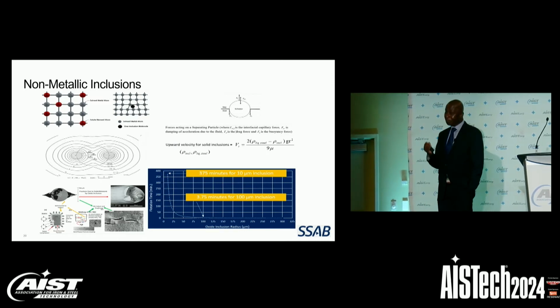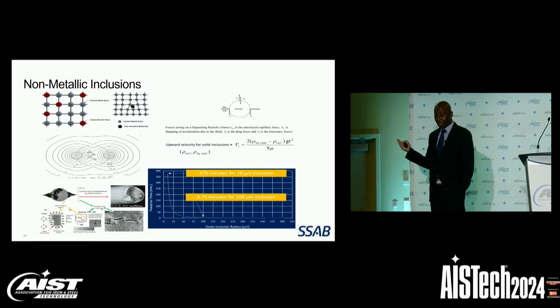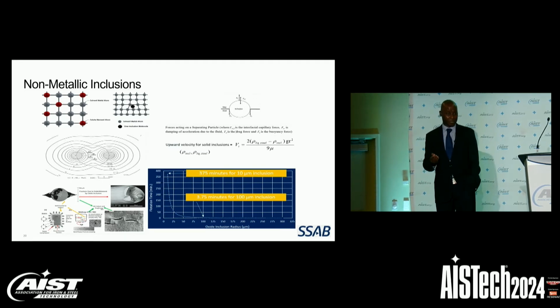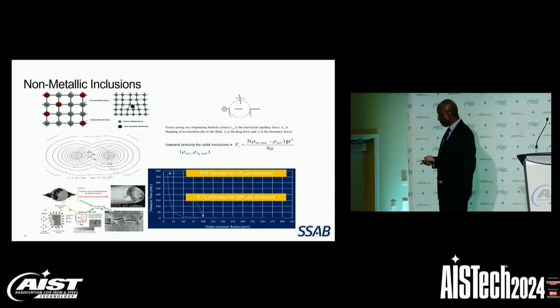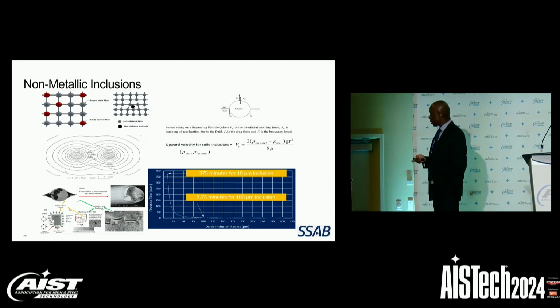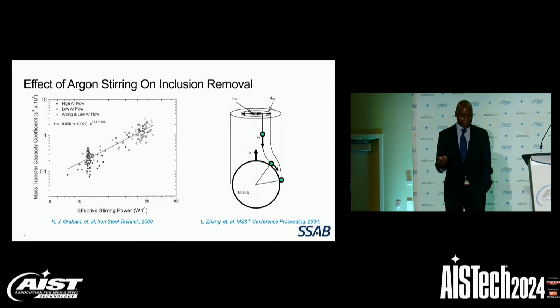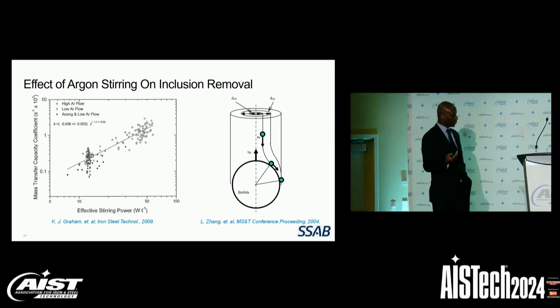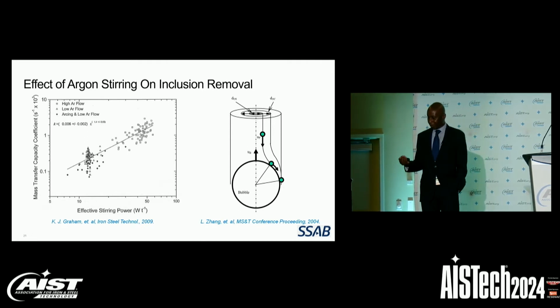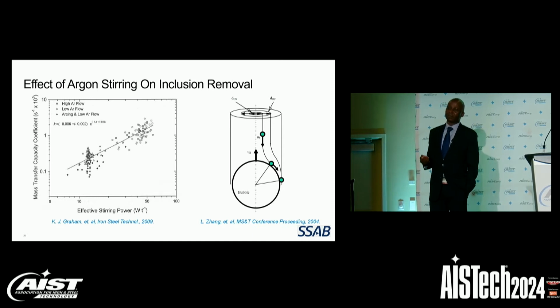But the 10 micron inclusions can be very detrimental to the mechanical properties if they are present in large population. But we don't have 400 minutes to waste. Otherwise, we will not be in the business of steelmaking. Some researchers have done work and shown that argon bubbling can enhance flotation of non-metallic inclusions during ladle refining.